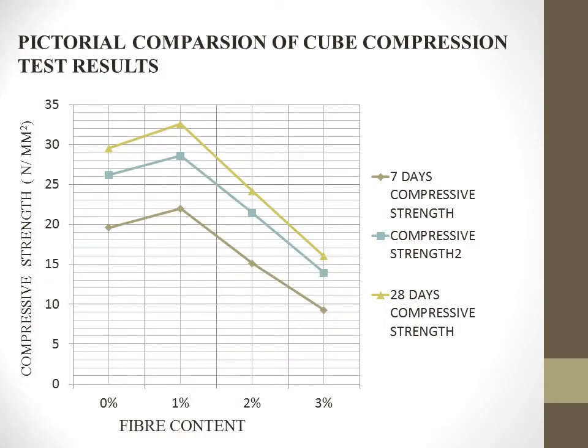As you can see in the graph, there is an initial increase, which means there is an increase with 1% of bamboo fiber, and then there is a gradual decrease for 2% and 3% addition of bamboo fibers.